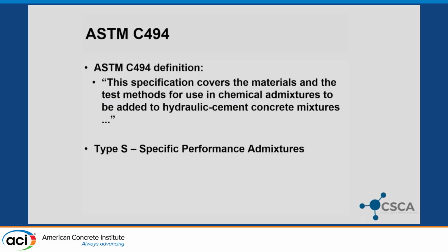Now, again, the science I didn't want to get too much into. What we're supposed to talk about today is the specifications. I know this might sound surprising, but colloidal silica does not have its own specification right now. So what we are using, and when I say we, I mean the royal we, as in the entire industry, is ASTM C494, the standard specification for chemical admixtures for concrete. The specification covers the rest. There's a Type S specification for a specific performance admixture. Now, this is totally performance-based, so that means we're running about a year's worth of tests, if not more.